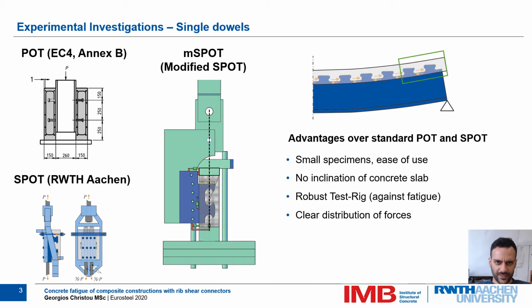Thus, a new modified single push-out test was created, as shown in the middle, in which the lines of action were identical and the test rig was designed with a very high resistance against cyclic loading. In the series of single push-out tests with the new test rig, we were able to reach up to 10 million load cycles. In our tests, we measured the slip, the rotation of the dowels, and the steel dowel's movement against the steel web by means of 5 inductive displacement transmitters.